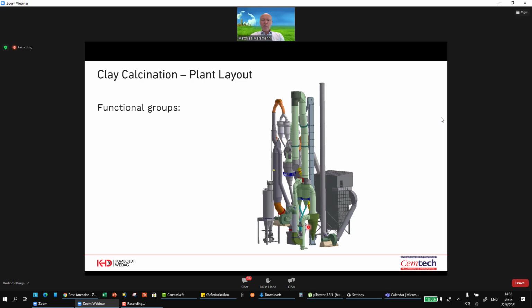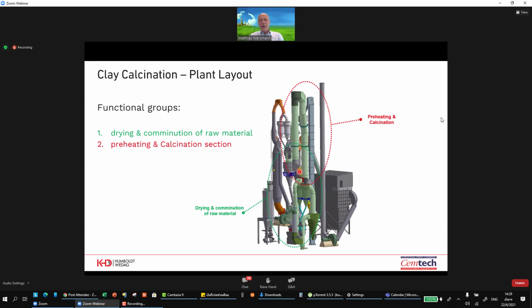And if you look at how this looks in a plant view, you see it comes very close to a conventional cyclone preheater, just a little bit rearranged, and the hammer mill introduced into it. So you see in green the drying and comminution part. In a red circle you see the preheating and pre-calcining part, which is the large visible flash tube calciner here. And then finally we have the recuperation and product cooling. So it's a counterflow process, highly energy efficient, like we know it from clinker production.